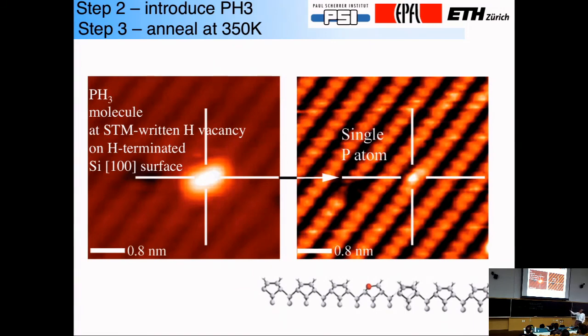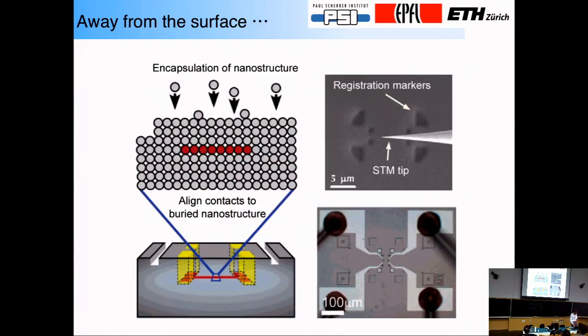And so in essence, what I have is a positive pattern, essentially a lithographic process now, for putting phosphorus in well-defined locations. Of course, after I've introduced the phosphine, the phosphorus actually binds very strongly into the surface. It actually substitutes for a silicon atom. At that point, I can actually anneal the whole business, get rid of all of the hydrogens, and deposit on